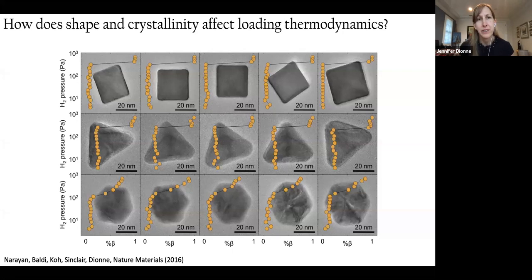So you'll see here for different size single crystalline nanocubes and single crystalline prisms that the isotherms show very abrupt transitions between the alpha phase, represented over here by essentially 0 or close to 0 fractional percent of the beta phase, and the fully hydrogenated phase. So we have these extremely sharp transitions for the single crystalline nanoparticles. If you compare that to the polycrystalline nanoparticles, for example, the icosahedral nanoparticles, you'll see that the isotherms are considerably more sloped and gradual.